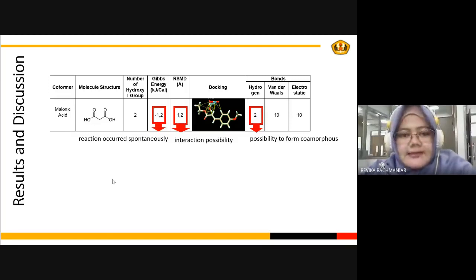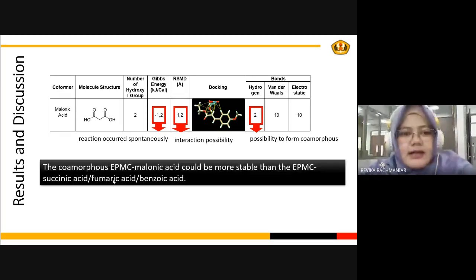So from this result, we see that some carboxylic acids have a chance of making hydrogen bonding: malonic acid, succinic acid, benzoic acid, and fumaric acid. But the coamorph of APMC with malonic acid has a chance to be more stable than APMC with succinic acid, fumaric acid, and benzoic acid, because the APMC malonic acid has 2 hydrogen bonds, and APMC with succinic, fumaric, and benzoic acid has just 1 hydrogen bond.